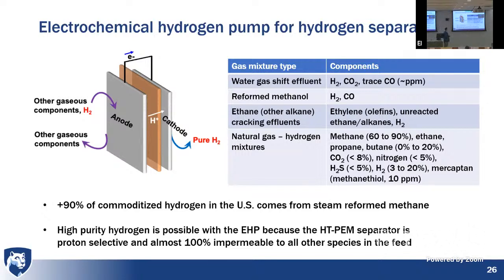And 90% of commoditized hydrogen in the US comes from steam methane reforming. But this membrane is really selective. All the other gaseous components wouldn't permeate across, and so you get really high purity hydrogen on the other side. And so what we're really interested in eventually, I won't show you this today, is purifying this hydrogen from natural gas mixtures. But I will be showing you how we've taken hydrogen from reformed hydrocarbons, heavy CO mixtures, and gotten high purity hydrogen. If you're cracking ethane to make ethylene for plastics and so forth, you might want to recover that hydrogen for use later on. And this pump can do it.